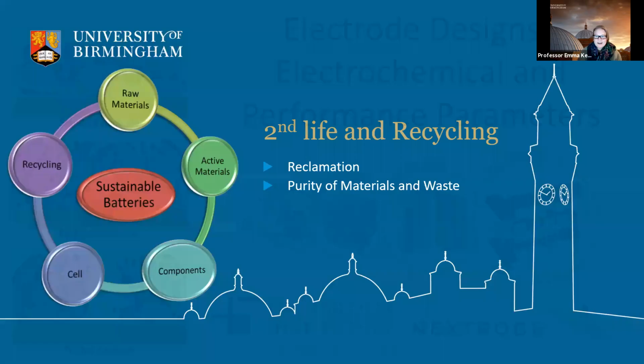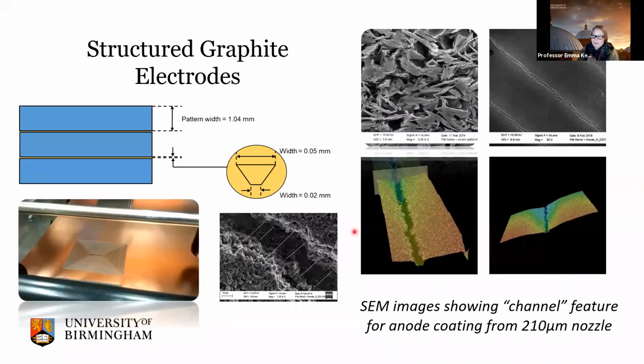So the first question is from Kunal, and he asks, how do you ensure uniform electrode thicknesses when depositing the slurry through the syringe? I see, that's interesting. We don't get uniform electrode thicknesses. What we're actually trying to do is optimize channels within the electrode to try and promote electrolyte transport, particularly for high power. But in this case, what it promoted was cycle life rather than power. And that's because I don't think the density of the electrodes was high enough, which meant we didn't have good enough electron transport throughout the layers.